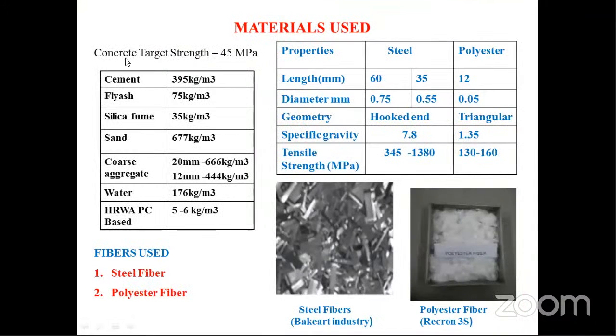So I have chosen a 45 MPa grade of concrete, and the mix design is as usual, as per the conventional method I have adopted. Cement has been added up to 395 kg, and fly ash has been replaced at 15%, silica fume 7%, and combined gradation has been done with two sizes of aggregate, 20 mm and 12 mm, and a high range water reducing PC based admixture has been used. This is very essential, and it is a new generation chemical admixture that is used for reducing the water requirement in the production of cement composites.